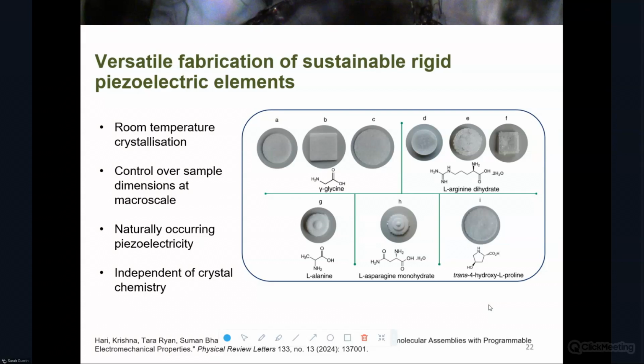Because if we're specifically taking on ceramics, we need to be able to grow molecular crystals in any shape, any size, any thickness, particularly at the macro scale. So one of the big goals of our ERC grant was this level of versatility, that no matter the chemistry of the molecule, you could crystallize it in whatever shape and dimensions that you want. So this paper just came out over the summer, where we could show that for normal crystallization conditions, you can mold the shape of these assemblies,